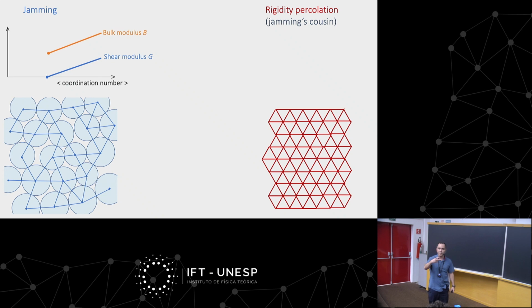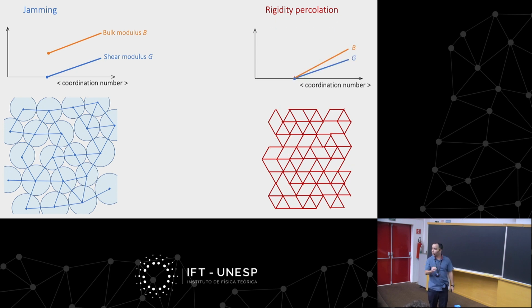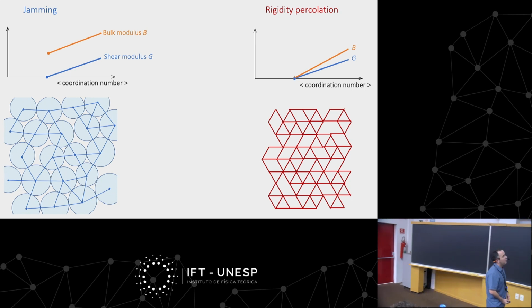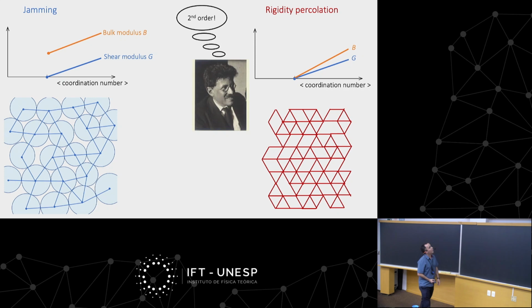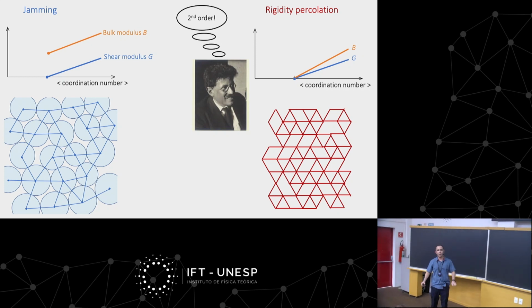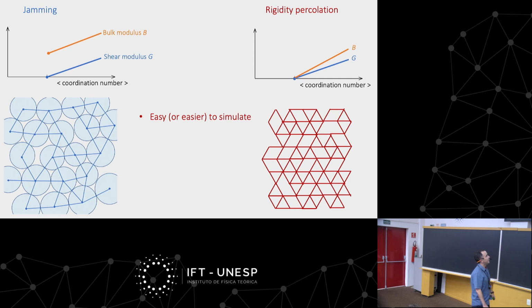But you can imagine that you start randomly removing bonds on this triangular lattice. And what happens when you randomly remove these bonds is that you get a transition that's much like jamming in some sense. The bulk modulus and the shear modulus go continuously to 0 at some critical coordination number here, or some critical average coordination number. But unlike jamming here, you have something that's clearly second order. All the moduli go continuously to 0. And so Paul Ehrenfest is much happier now because it's easier to classify.